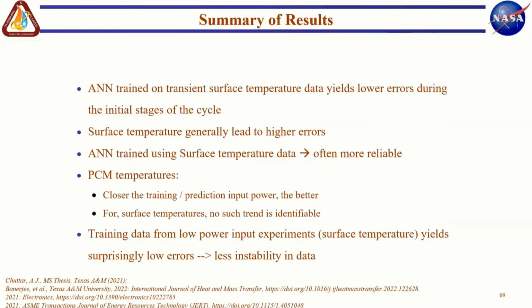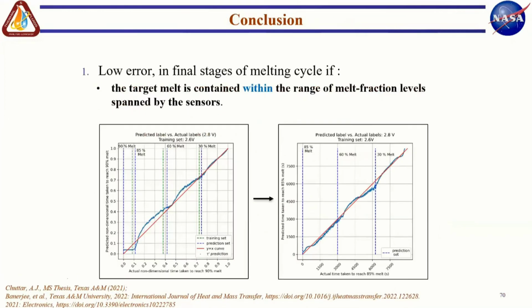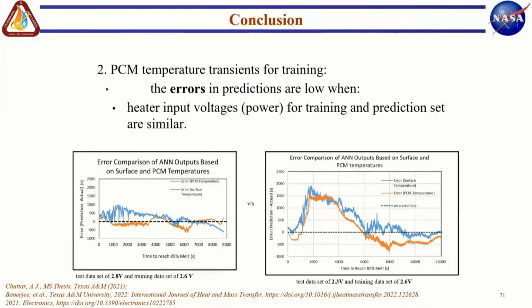And so as a summary, as a conclusion, we get low errors as long as we are predicting within the manifold of our measurements. In other words, if my measurements are for 30, 60, and 85, and I'm trying to do the prediction for 90%, which is outside the measurement envelope, my error is higher. On the other hand, if my prediction is within the measurement envelope, I tend to get lower errors in my prediction, specifically if I'm using the PCM temperature data.